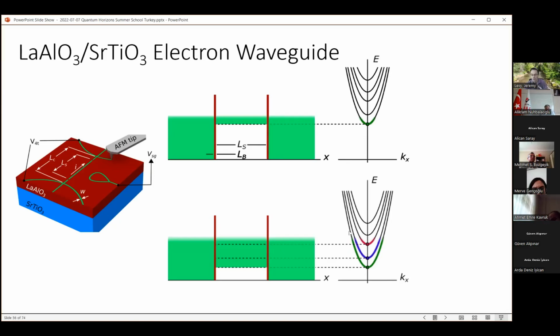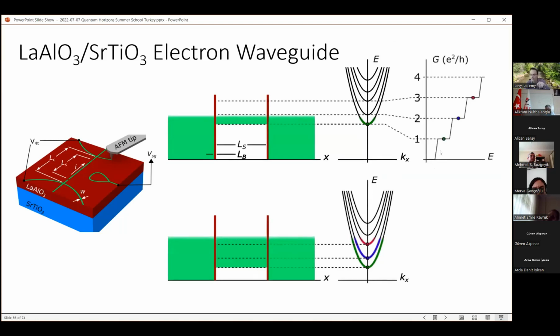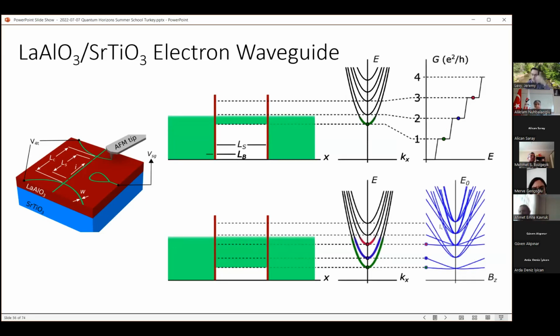And so you should get 3 times the conduction that you get over here. Each occupied subband gives rise to a conduction of e squared over h. So what you would see is that as a function of the energy or chemical potential, you would see these steps. And the bottoms of these subbands are when you jump from a lower conductance state to a higher conductance state, and that can also depend on magnetic field.